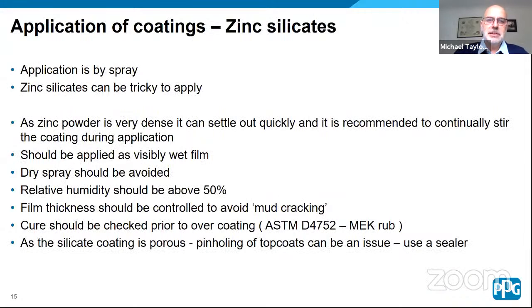Application of the coatings. Zinc silicates generally have to be applied by spray application. They can be tricky to apply. It's very important that, once you've mixed the binder and the zinc dust together, you continue to mix the coating when you apply it, mainly because the zinc powders are very dense and settle to the bottom, so you need to keep it in suspension.